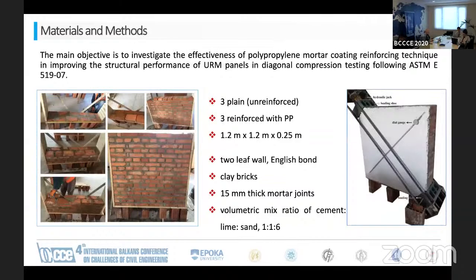The experimental campaign that we did was conducting a set of diagonal compression tests as of ASTM 519, which is the American standard for testing of diagonal compression. We should understand that this technique can, let's say, imitate what an earthquake can cause to the wall, but using static loading. We use three plain unreinforced masonry walls made of 1.2 by 1.2 meter and 0.25 meter thickness. And we also use three unreinforced masonry walls, then reinforced with polypropylene mortar coating.